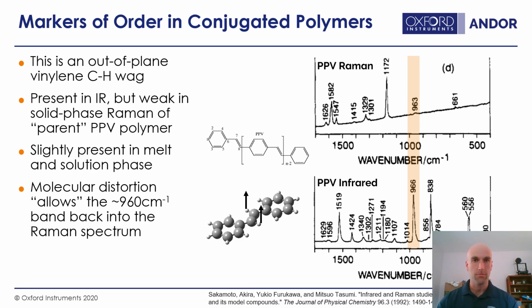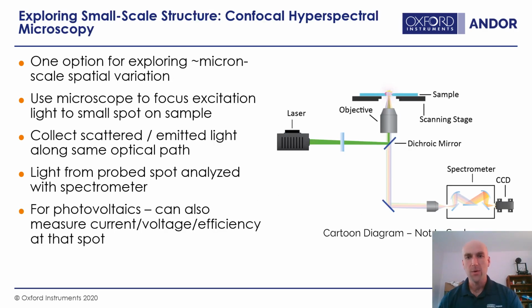So what I just described is still a bulk measurement, which is to say it averages over a large area or the whole of the sample, and doesn't tell us anything about the point-to-point or the local variation and how that packing works. So one option which we could do to unravel that micron or sub-micron spatial variation is to do confocal hyperspectral microscopy, and that is simply that we're going to illuminate one point of the sample, as small a point as we can using a microscope, and then record a spectrum that corresponds to the scattering and emission from that point.